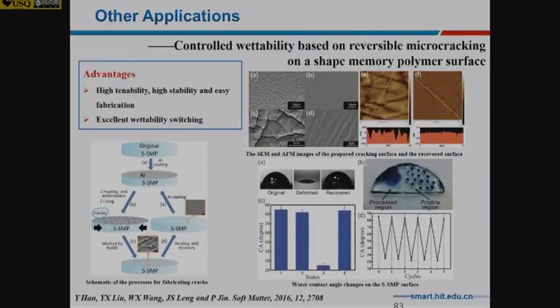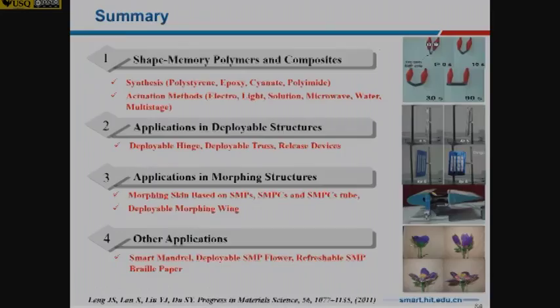So this is another design using shape memory polymer. You can see this is the original shape, which has micro cracking, and this one is the recovered shape, which you can see is very flat. With this one, you can see this micro shape changing, which means this one can change the contact angle. With the contact angle changing, we can control the wettability. The wettability can be changed and controlled by the micro cracking. You see this one, and here as well.